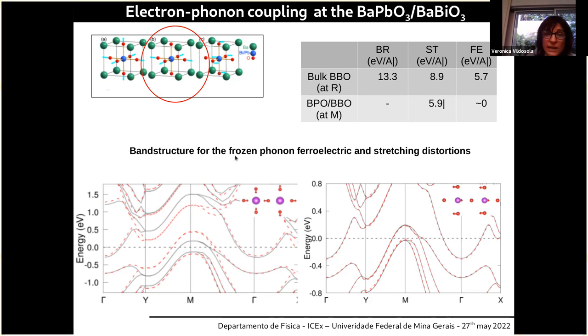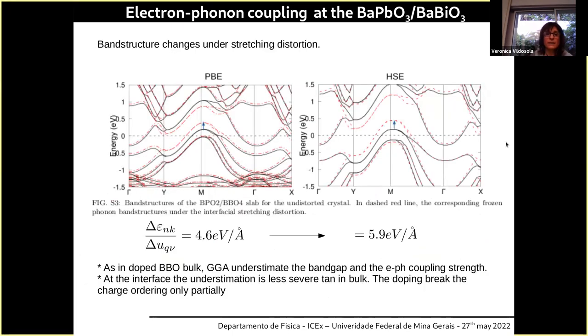So the only operating collective mode that is connecting with the electrons is the stretching interfacial mode. And we calculate the couplings for these modes, and we do it with PBE, and also with the hybrid functional. The PBE is the GGA, and we obtain that with GGA we get like 4.6 electron volts per angstrom, and this value increases to 5.9 electron volts per angstrom.